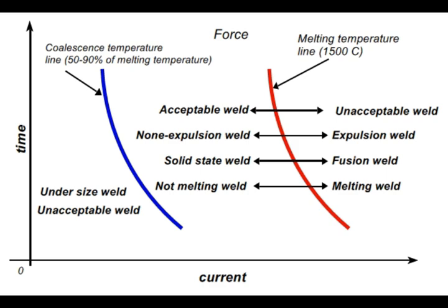Expulsion weld is a fusion weld, non-expulsion weld must be solid-state weld. Solid-state weld is a not melting weld, fusion weld is a melting weld. The line that divides the not melting weld and melting weld must be the melting temperature line. On the right of the blue line is acceptable weld, on the left of the blue line is undersized weld or missing weld. The blue line must be the minimum coalescence temperature line. In Elihu Thomson's patent US 444,926 he called it necessary temperature line. In other words, acceptable weld is a non-expulsion weld, solid-state weld, and not melting weld. Expulsion weld is an unacceptable weld, fusion weld, and melting weld.